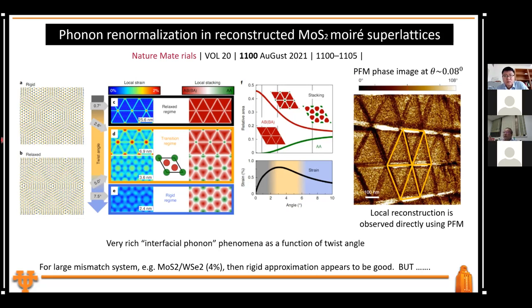So in that paper, it also said that for a low twist angle, you're going to have this 3D reconstruction. Basically what this means is, locally, if you are rigid, then you will see a very regular moiré pattern. But if locally they deviate slightly from the so-called perfect stacking, like the edge stacking or the R stacking, they want to locally push so they become commensurate. So locally this part is pushed to a commensurate structure, and the accumulated mismatch gets popped in right at this interface, from all those sharp lines, and accumulated over here. But if the twist angle is large, such a large 3D reconstruction is no longer favorable.